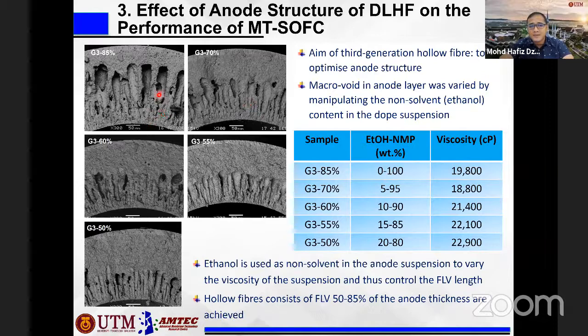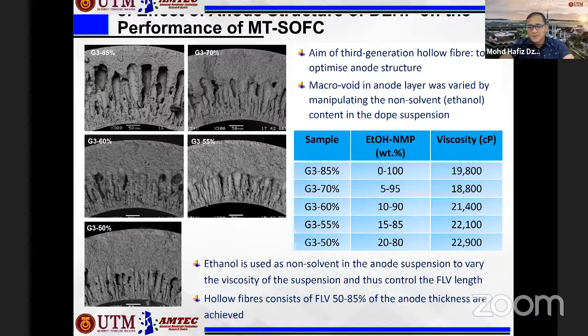But the drawback of these finger-like structures is that they can reduce the mechanical strength of the membrane, because the finger-like structure is actually a defect. This microvoid can be called a defect. So if you have too many defects, it will reduce the mechanical strength. Therefore, you have to keep the finger-like structure at an ideal amount and ideal length in order to produce a good flow of fuel.